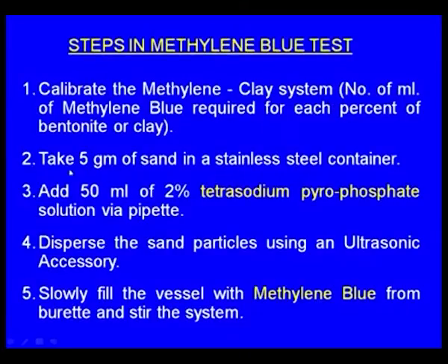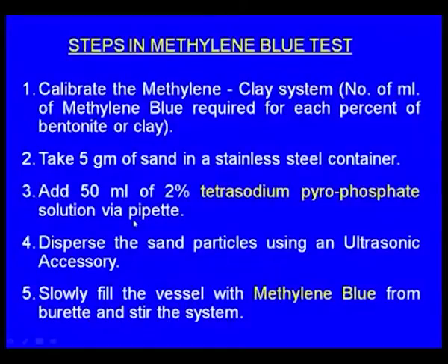Next, in the second step, the first part was the calibration, the second part is to take 5 grams of the sand in a stainless steel container and add 50 ml of 2% tetrasodium pyrophosphate solution via pipette.